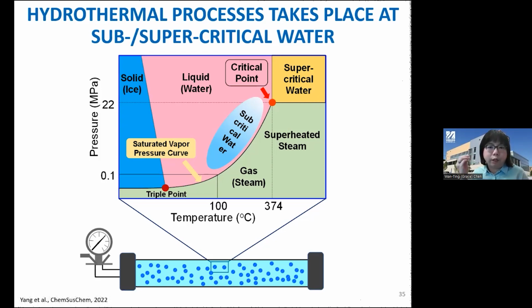And at this supercritical state, water can enjoy the transport properties, the advantage of gas, but also the advantage of liquid. The diffusivity will be nice, while the viscosity will be reduced. So you enjoy a lot of benefits, and that's why we study that. Another terminology is called subcritical water, where it's not gas anymore. By applying a little bit of pressure, we maintain water as liquid, even as we increase the temperature.